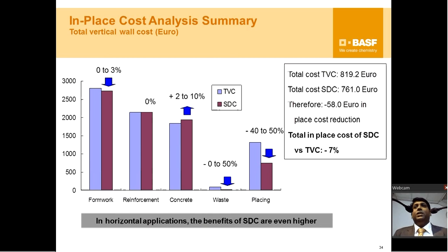You have a segregated mix initially, but in a self-compacting concrete or a smart dynamic concrete, you cannot have any segregation happening. So you not only need a high flow, you need something which can also make the aggregates float in the concrete, or put them in a suspended mode. Aggregate has to be suspended in the body of the concrete, and what makes it suspended is the viscosity modifying agent. So the solution we have in the name of Master Matrix is now a part of the PCE, and that is what makes the concrete highly flowable, helps the concrete compact of its own weight, and also takes care of the suspension of the aggregates. So that's the background of the chemistry behind what this admixture is all about.